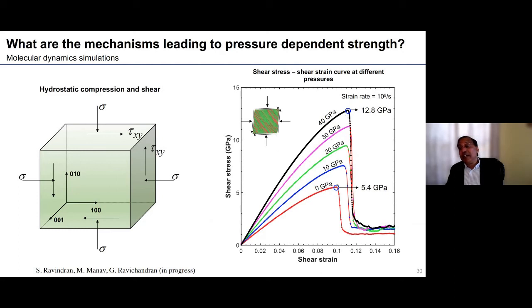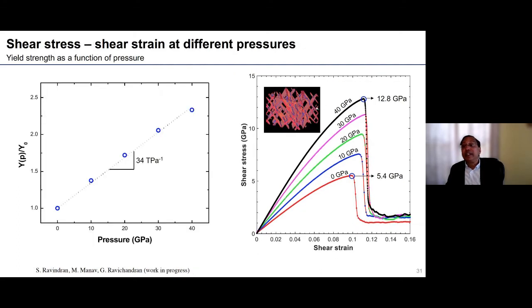Here, obviously, as we know, this is defect free initially. So we get this very high strength. And then we can look at the different dislocation structures which form using these MD simulations. And what we find is that we can find the yield strength. So we had a value of 65 in our experiments. The molecular dynamics simulations are giving us a value of about 34 or so.